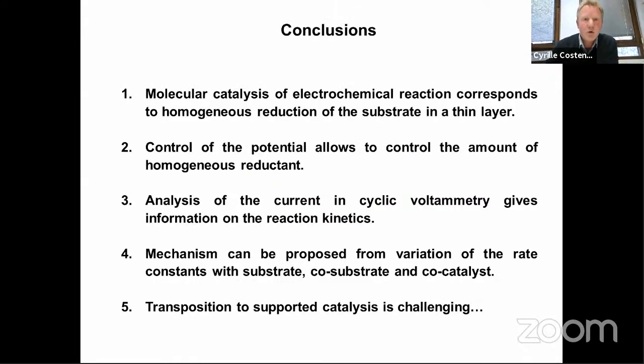So now I will conclude that I tried to show you that molecular catalysis of electrochemical reaction corresponds actually to a homogeneous reduction of the substrate in a thin layer close to the electrode. If you really have homogeneous catalysis, then you can control the amount of catalyst you generate by controlling the potential of the electrode, of course, and you can analyze the current in cyclic voltammetry to get kinetic information, okay?